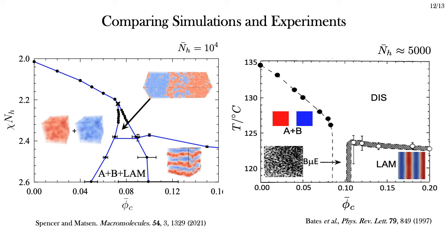These structures evolve very slowly. Macrophase segregation is particularly slow due to large length scales over which polymers need to migrate. This combined with the small free energy cost of the microemulsion deviating from its preferred domain spacing, it's easy to see how squeezing excess homopolymers out of the microemulsion to create these A and B rich regions may simply not have occurred in the time over which these experiments were conducted.